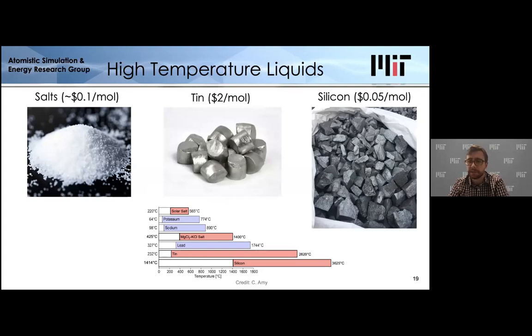Now, there are some practical challenges associated with silicon involving its high melting temperature. So it melts at around 1400 degrees Celsius. So freezing is an issue. If any part gets below that temperature, that becomes a problem. Another big problem with it is that it's a lot more reactive than tin. So tin is very nice and stable, specifically with the materials that we've experienced it with, graphite, a main one. Silicon, unfortunately, does not have quite the same level of stability with graphite, which is basically our real workhorse in terms of piping and pumps and containment and everything.